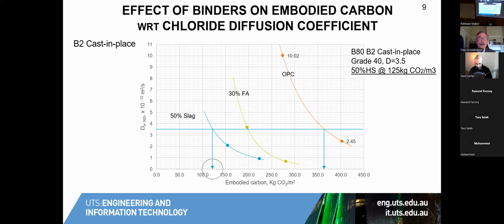Okay, so for exposure B2 cast in place that I pointed out, I just share with you different concretes: one with strictly ordinary Portland cement, a concrete with 30% fly ash, and a concrete with 50% slag, just to show an example. And in this case, you'll find that to meet the diffusion coefficient of 3.5, the best type of binder system in this example is the 50% slag, which basically will demand an embodied carbon of around 125 kg of CO2 per cubic meter.